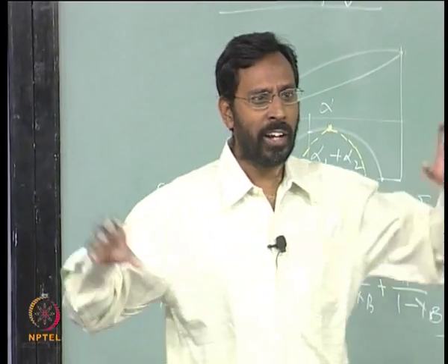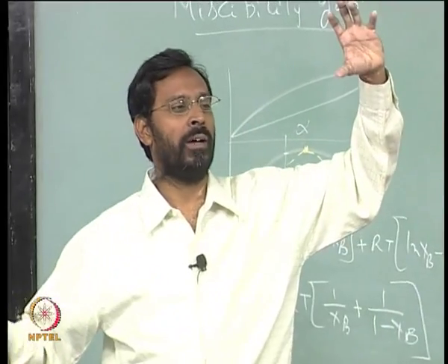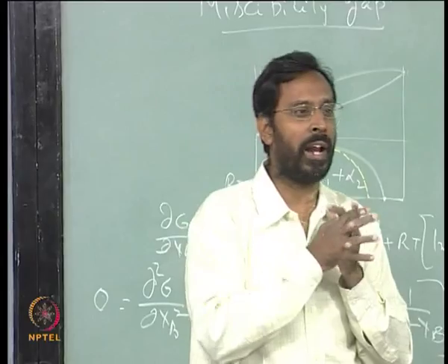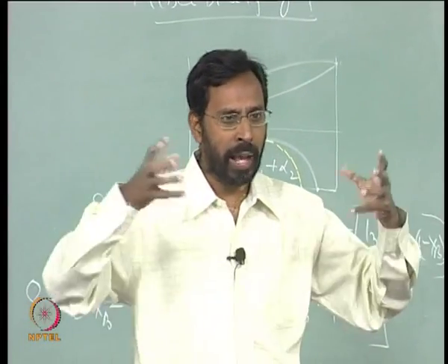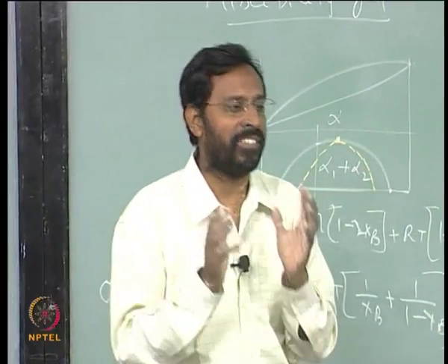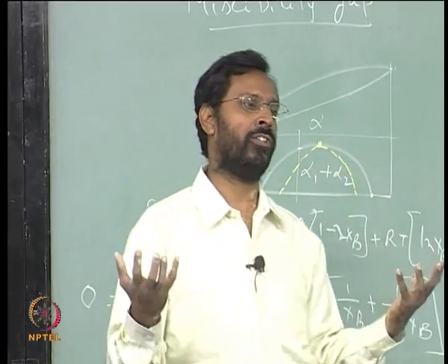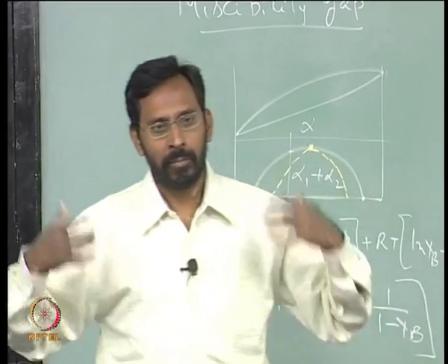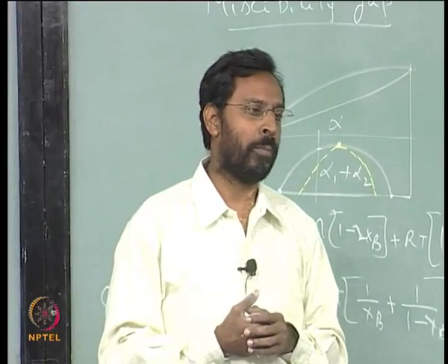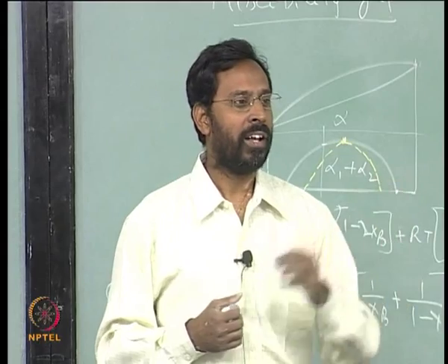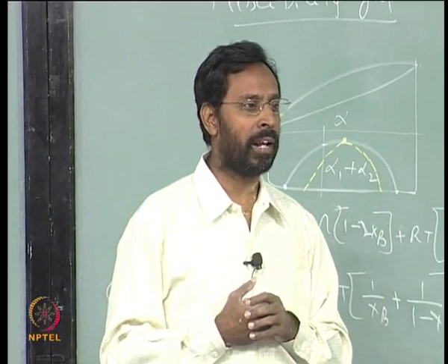They say that if I take one element with a bigger atom and another element with a smaller atom, then the smaller atom fits into the bigger atom lattice and makes the whole packing very dense, and the moment dense packing is obtained, the structure is more stable. So whichever makes such a dense packing possible, you would see it is stable. For example, the best zirconium based bulk metallic glasses are zirconium beryllium.